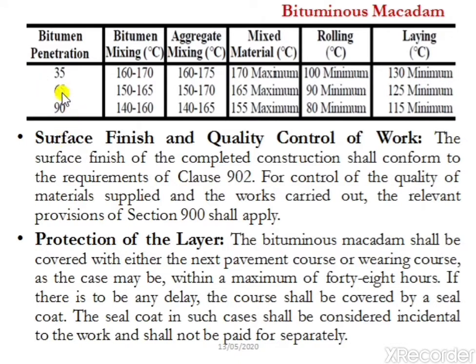with a penetration value of 65, the bitumen mixing is done at a temperature of 150 to 165 degrees Celsius, and the aggregate mixing is done at a temperature of 150 to 170 degrees Celsius, and the materials are mixed together at a temperature of 165 degrees, and it is the maximum temperature. The rolling is done at a temperature of 90 degrees Celsius, and it is a minimum temperature, and the materials are laid at 125 degrees minimum temperature.